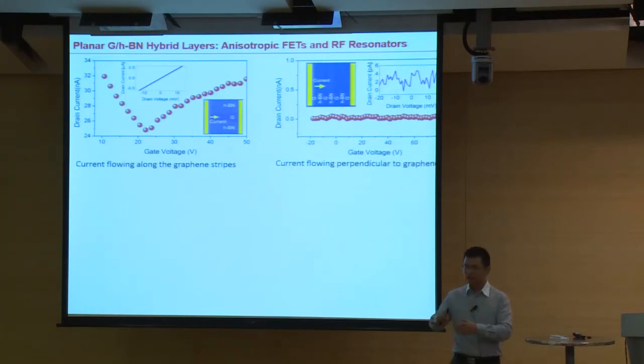And okay, if we make a structure like alternating strips of graphene and boron nitride, we can get an image like this. There's a sample, and if we put contacts in this way and the current flows along the graphene channel, we can get mobilities comparable to pristine graphene. And if the current flows perpendicular to the graphene and boron nitride strips, then we get nothing. So structurally, we actually get anisotropic FET devices.